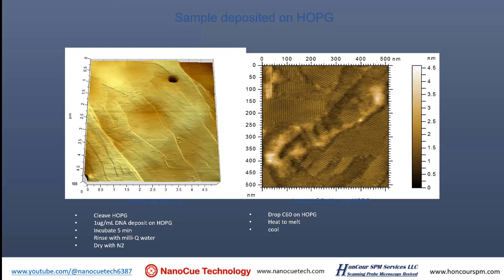And sometimes people use this image to challenge some AFM, saying, hey, if you're high resolution, how come you cannot see atomic arrays or molecular arrays of this sample? The reason that in the early days AFM scientists used this image to challenge each other is a trick story. It is not always the resolution of the instrument or the sharpness of the tip that matters. It also matters where you image. Because these self-assembled C60 layers don't always form naturally. They form when the droplets of C60 are flat, not when they're like a bulk. So if you see a bulk, like little beads on the surface, and you image on it, there's no assembly. Only in the flat areas can you see those assemblies.